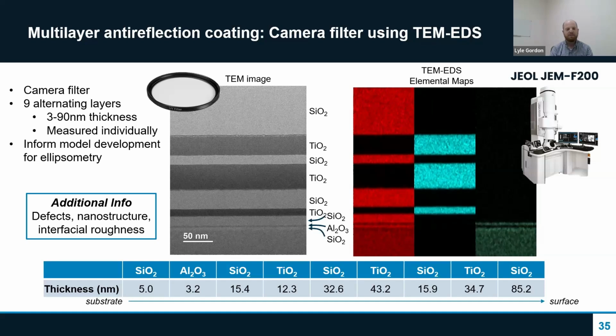And this sample is way too thin to just look at with an optical microscope. So we prepared a TEM sample using a focused ion beam, and then you can really clearly see all the individual layers and count them, including a really thin little aluminum oxide layer. And in the TEM, we also have elemental sensitivity using energy dispersive X-ray spectroscopy, which is similar to X-ray fluorescence. So you can map different elements and determine the composition of the film. In this case, we can see the alternating silicon-rich layers, which are the silicon dioxide, and then the titanium-rich titanium dioxide layers, and they're all on top of that glass substrate.